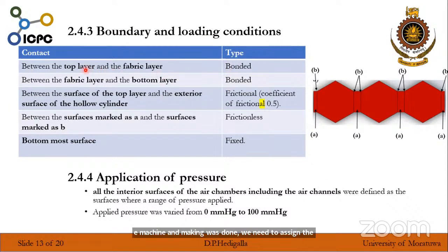As I mentioned earlier, the mini bladder was a 3-layer device. So the top and fabric layer were bonded, and the fabric layer and the bottom layer were also bonded, and the interface between the top layer and the exterior surface of the hollow cylinder was considered as friction. And between the surfaces marked as A and B, it was considered as frictionless, and the bottommost surface was considered as fixed.